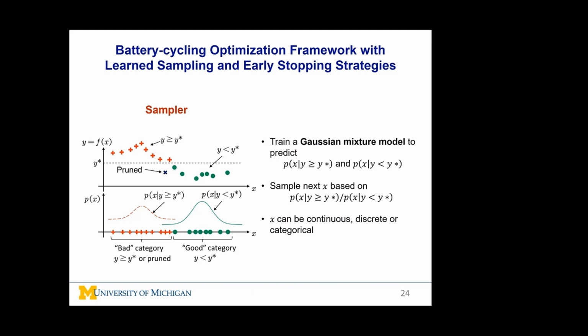Our key idea is to leverage all that middle data, the battery data that has stopped before reaching 1,000 cycles, and many of them stop very early. So we can leverage this data and use our sampler to output the configuration that is most likely to be the best one. This is achieved by a Gaussian mixture model.